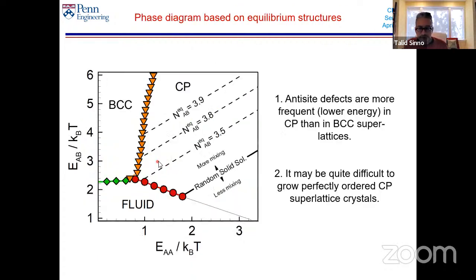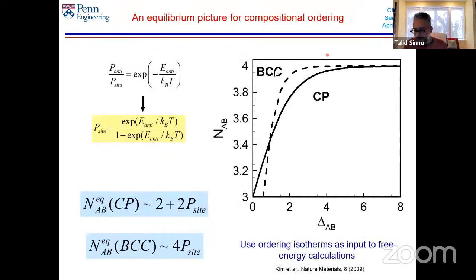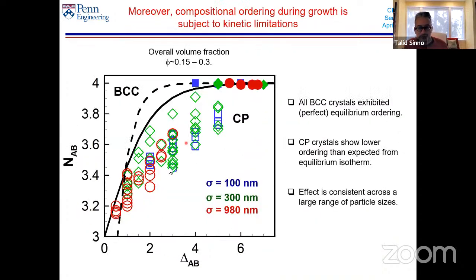So this is the same figure. I just want to go back to here. This is the same figure as this. This is the isotherm based on equilibrium. This is what you actually see based on running simulations. And each of these points, what it's telling you is that the hollow symbols represent close packed crystals. The solid symbols represent BCC. So what you see is all the BCC cases always lie up here. So they're always perfectly ordered. And all the close packed crystals lie below the isotherm.